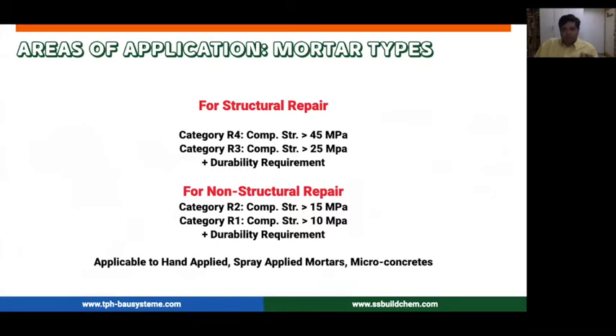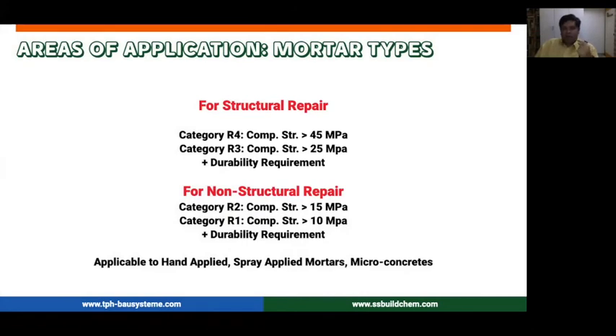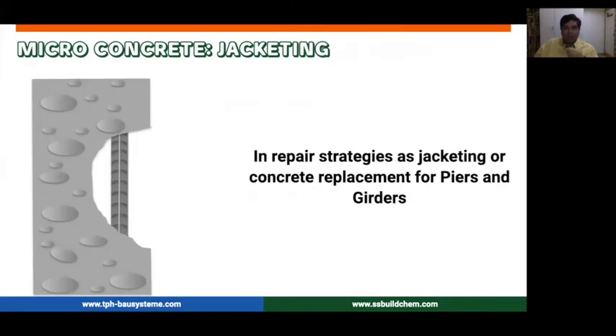Based on the international standard EN 1504, if you're looking at structural repair, then very simply what you need is a compressive strength of more than 25 or more than 45. So this is category R4 or R3, and they also have some durability requirements. So they're very clear about what mortars can be used for what purposes. Your mortar compressive strength should be matched very closely to your substrate. So if you have a substrate that's M30 or M35, you shouldn't use a mortar which is, say, M70 or M80. It's not required. It should be matched pretty closely to your basic substrate.